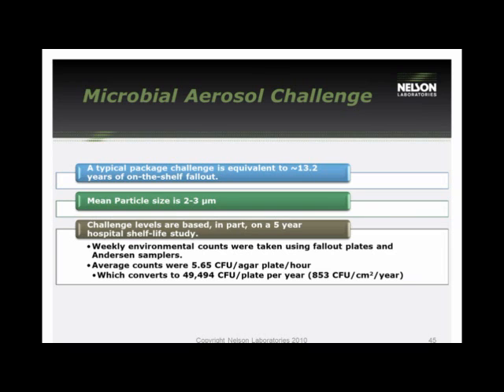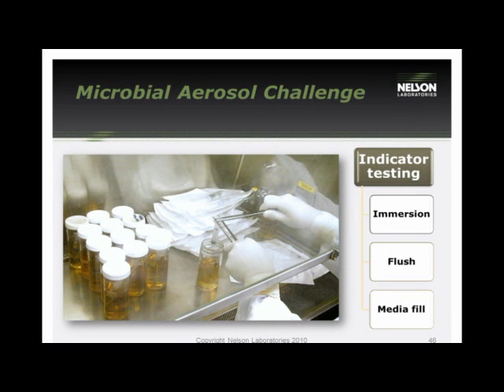Additionally, in conjunction with the challenge levels, you want to keep sight of the particle size. The particle size can range between 2 and 3 microns. At the end of the aerosol test, you remove the samples and perform an indicator test. This can be performed using immersion, flush, or media fill, but it is very important that there be contents inside each of these pouches for us to do this test on.